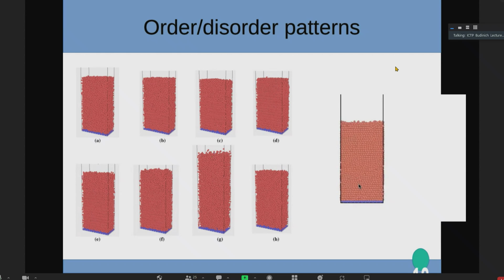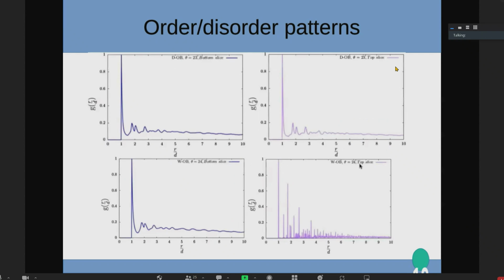and in this case we have two-dimensional FCC layers on top of each other, and in this case there is a very small friction between layers, and due to fluctuation of particles, suddenly a fluctuation increases the disorder in the system, and the system moves to the disordered structure. This pattern continuously appears and disappears.